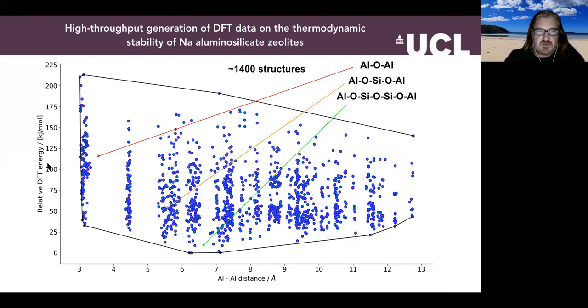We've got relative energies here, and the distance between aluminium atoms within the structure. This is one particular concentration of aluminium that we've examined. We can see that the lowest energy structures are associated with these types of sequences. This is what we would call the next nearest neighbor. It's less favorable to have this type of sequence and least favorable to have these linkages here, aluminium, oxygen, aluminium. And I'd like you to try and keep hold of that thought.